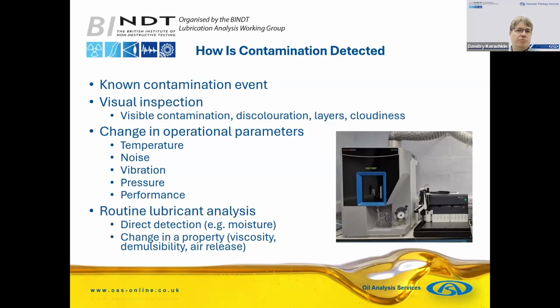And then another potential avenue is through routine lubricant analysis. Either the lab has detected contamination directly, for example, ingress of moisture or an increase in water content, or we notice a change in a property, such as viscosity, demulsibility, or air release, something that can be affected by contamination. Then we may want to investigate and find out what the actual contamination is, but we have detected its presence in an indirect way through a property change.